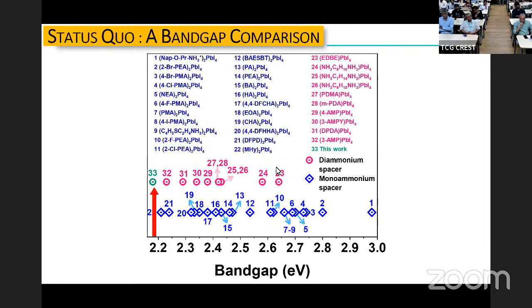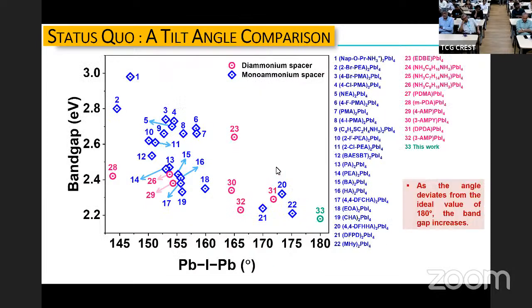Now, we tried to find out what really makes it tick. Why does it have the lowest band gap? Which structural aspect? Because eventually it is a structural aspect, since all of them are PbI4. You can see the inorganic unit is the same. It is the organic unit that is changing, but the organic unit does not directly control the electronic band gap. That's the property of the inorganic unit. So it's something about the PbI4 that is changing because of the organic, and that is changing the band gap, right? It turns out that it is the Pb-I-Pb angle that controls it largely. Other things also influence it, but the most important influence comes from the Pb-I-Pb angle.